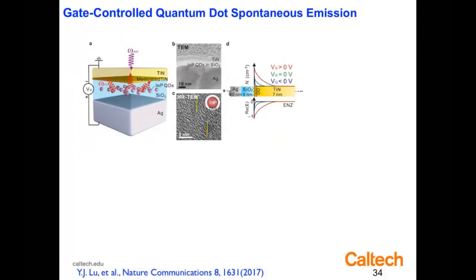So another thing that we can do, I talked about changing the emission rate. And Giuseppe asked me yesterday, can we change the emission rate of quantum emitters? This is a case where we're using a titanium nitride material, similarly changing it from plasmonic to dielectric. And we have this embedded in a little transistor-like structure where we can shine light through and pump and excite luminescence in indium phosphide quantum dots. These are the same indium phosphide quantum dots that are inside the quantum dot TVs you can now buy from Samsung in your local Circuit City or Fry's Electronics store.